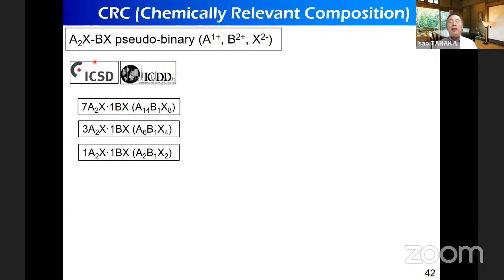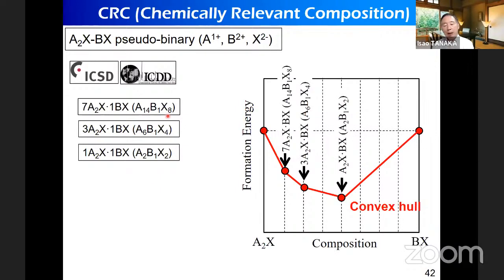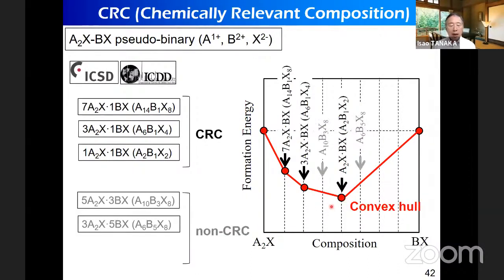If you look at ICSD, like in the previous tin molybdenum oxide, you can find this type of compound as an example. And they may be located on the convex hull if you perform first principles calculation or thermodynamical experiment. They correspond to chemically relevant composition, which means it is feasible to form crystalline phases, stable crystal phases. And the other composition, like these composition, which do not form crystalline structure, are categorized as a non-CRC. So we want to distinguish CRC from non-CRC.